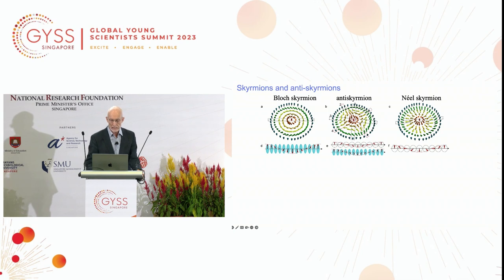Now, like the earlier domain wall, you can also form these skyrmions with a Néel domain wall, similar to the domain wall I showed you in our racetrack. In this case, the magnetization rotates outside, it's pointing up. Inside this object, it's pointing in the opposite direction. And along this radius, the magnetization rotates in a chiral direction. In the Bloch skyrmion case, the magnetization rotates not along the radius, but perpendicular to the radius along the tangent.